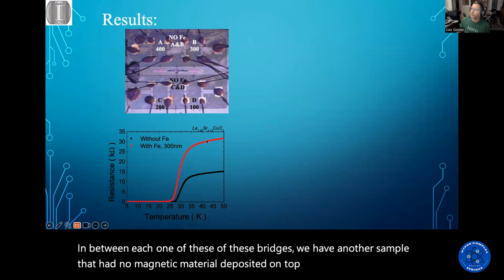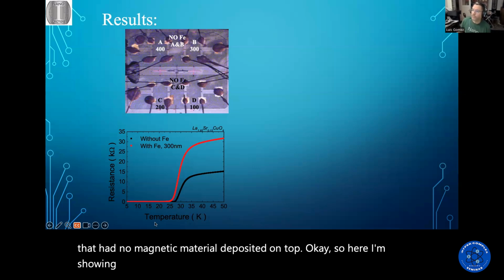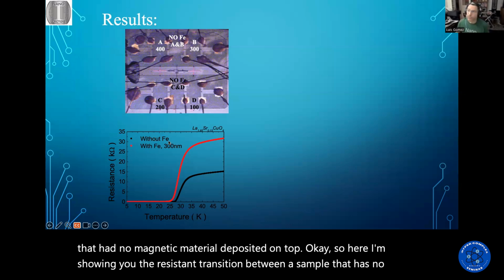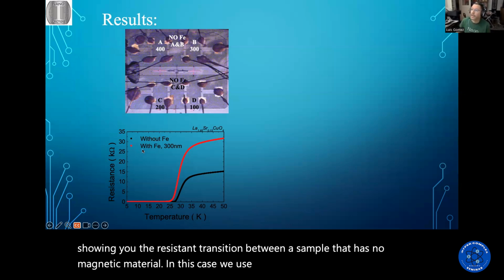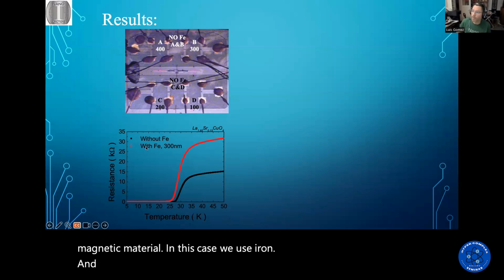Here I'm showing you the resistance transition between a sample that has no magnetic material. In this case we use iron, and what happened with the resistance transition of a sample that has iron deposited on top.